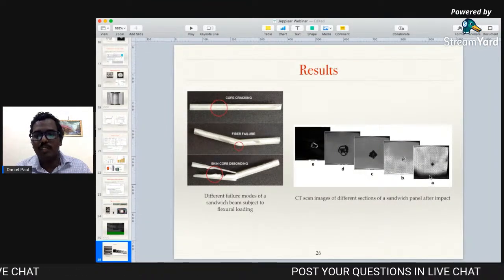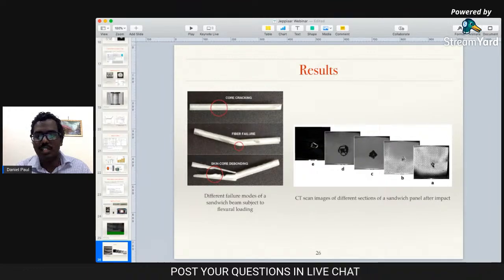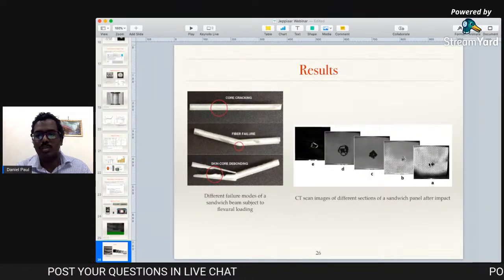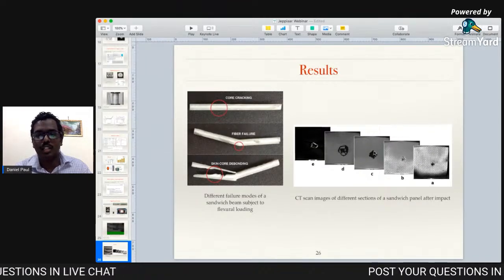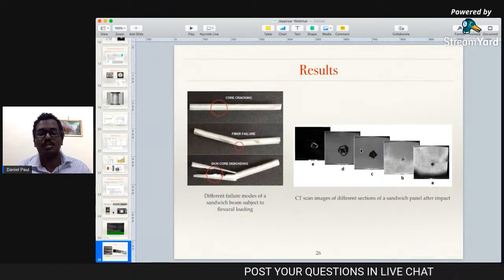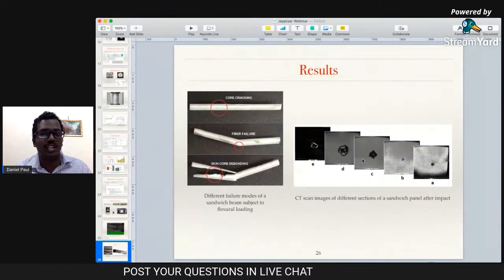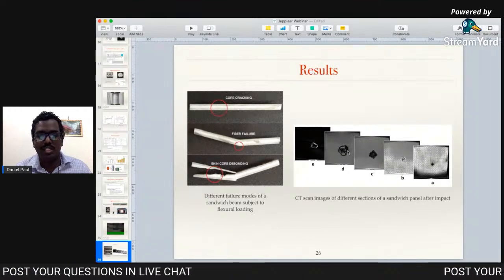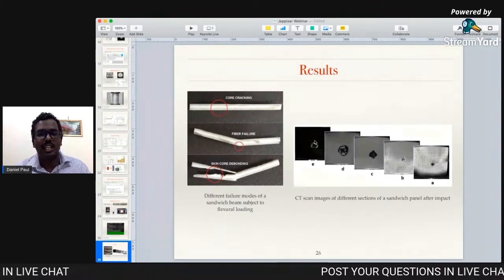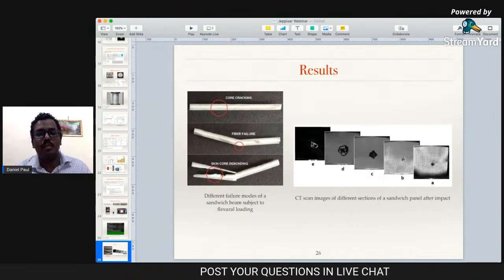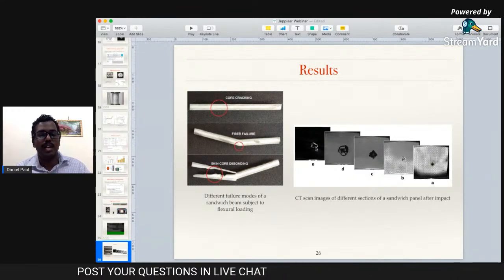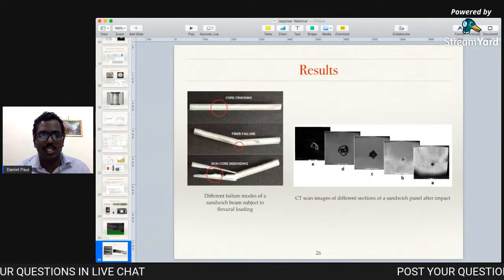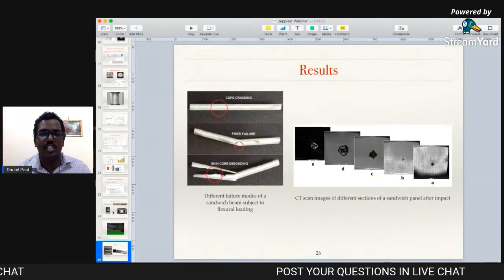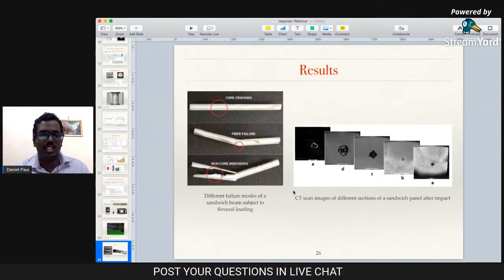So in A and B, we see the front skin, and we can see the impacted area in which the projectile has penetrated. And the syntactic foam is just matrix and hollow particles, which is a brittle material. So you can see a brittle failure here where this entire area has failed. And again, this E is actually the back skin of the material, through which we can see that the projectile has completely penetrated and caused kind of a petal formation here.